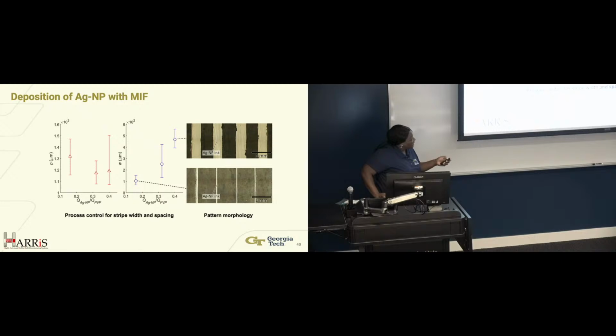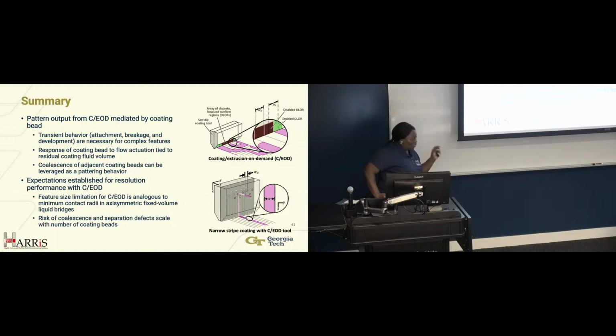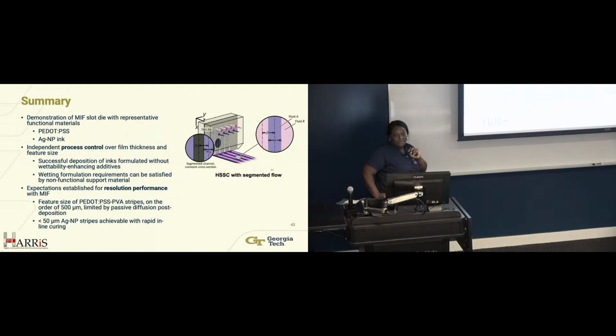So we went one further, and this is showing the difference between feature sizes as a function of Q. Here we have much wider, and then we decrease, and as you can see, the lines get more and more narrow. Pretty awesome work, if I don't say so myself. With our new technologies, we can control shape, structure, pattern, and feature size, depending upon the implementation of the tooling that is used. We can maintain the quality as long as we continue to meet the balance between the flow rate and the substrate speed. And yes, nanomaterials can be processed using these methods, among others.